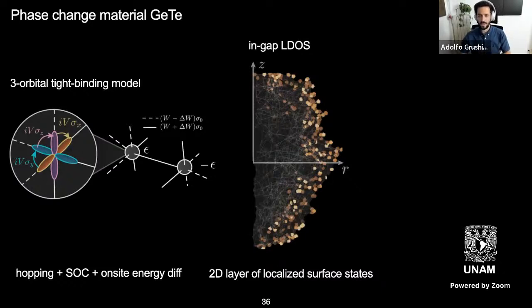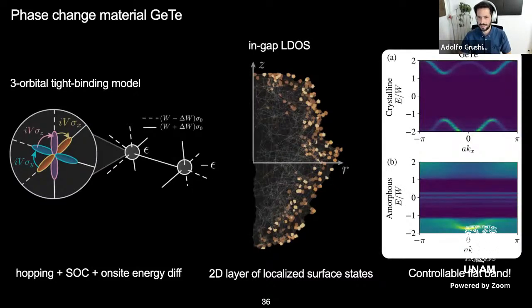And if you would go and ask your ARPES, your photoemission colleagues to measure this, you will see that essentially these states, because they're localized, will form a set of flat bands. The reason there are many of them is because this model has multiple orbitals and multiple sites, and so there are several bands. But what's important here is that, in principle, by an external perturbation, be it light or a pulse of current, you could change from the crystalline phase, which is like a trivial semiconductor, to the amorphous phase, which has these nice flat bands. And this procedure is relatively generic. You can also think, instead of SSH chains, which I started with, you could also have Kitaev models if you're interested in superconductivity, and you will get flat band Majoranas essentially.